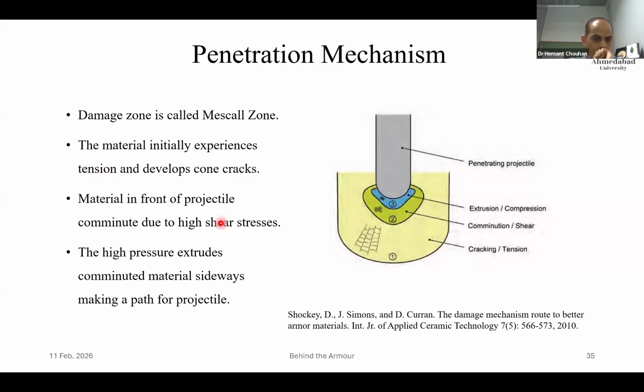Then we have this projectile, which will try to compress or push away the ceramic material in front of it. That will lead to the breaking down of the ceramic tile into a powder. We call it comminution. Because of the high shear stresses, the solid tile is now being converted into a ground powder kind of a thing. And then there is a high pressure which will try to extrude this material to the sides, and the projectile will keep on moving further down. So this entire mechanism will ensure that the energy is absorbed, the projectile is ground suitably and broken down, and if backing is sufficient, my ceramic will retain its position without giving way to the projectile.